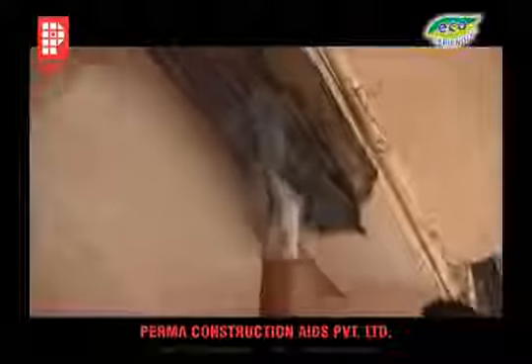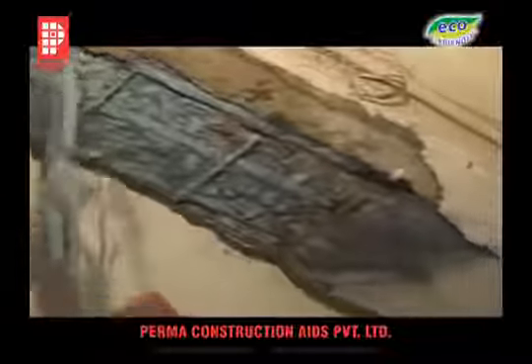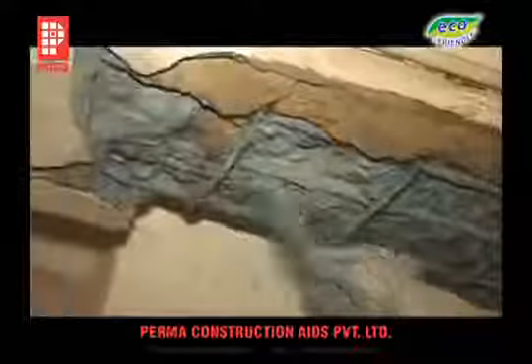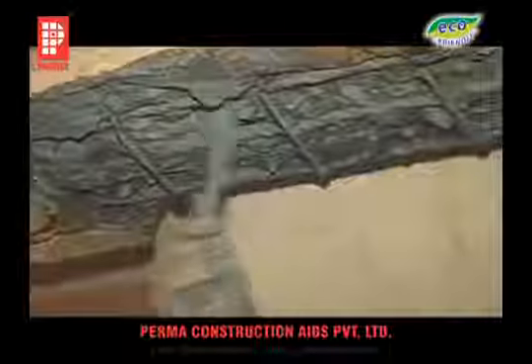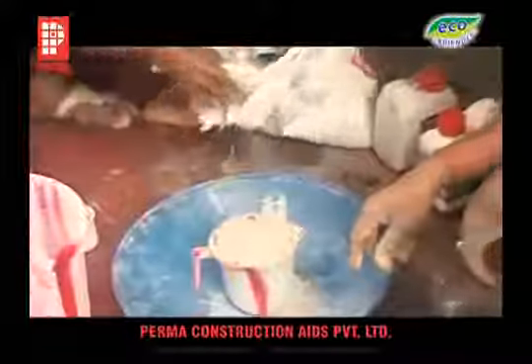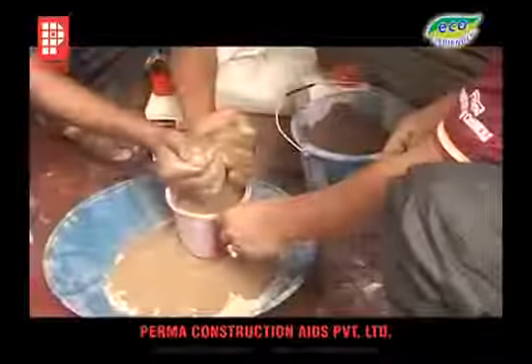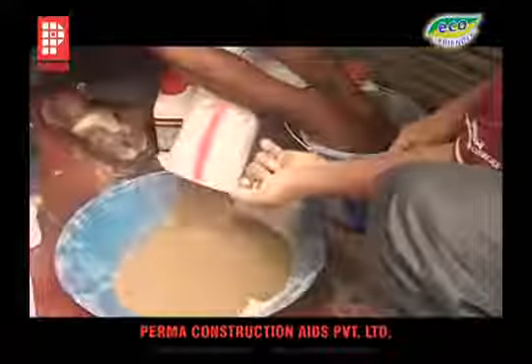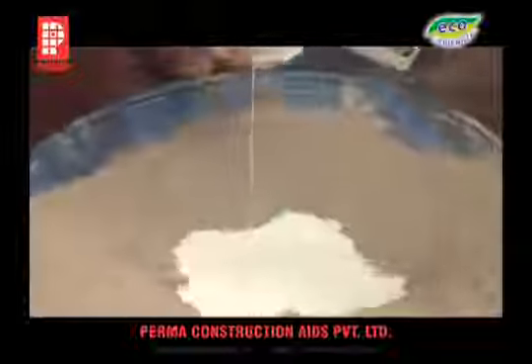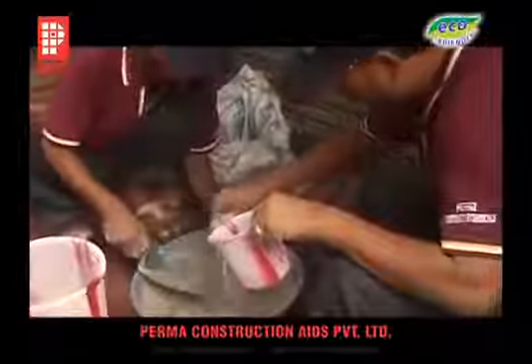After this passivator coating dries up, say after an hour or so, the concrete surface is made good with a mortar, prepared by mixing 1 kg of cement, 2.5 kg of Zone 2 sand, 200 ml of Perma Bond SBR and 150 ml of water.